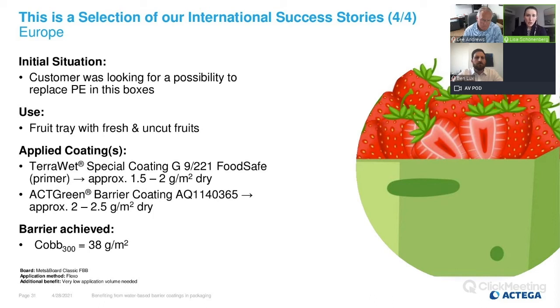Using a combination of a primer and a water barrier coating on a fully coated folding box board, we were able to achieve a Cobb300 of 38 grams per square meter with an overall very low application volume of 3.5 grams per square meter dry. And we could keep the customer more than satisfied.